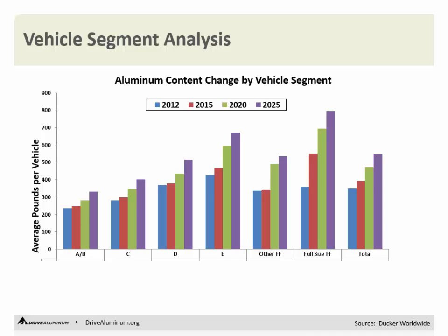And what we see is very significant growth in aluminum content for the full-size, full-frame trucks, also for E-Series vehicles. And it's a fairly continuous, pretty steady growth between 2012 and 2025. There's continued growth in all segments of the vehicle lineup, but the major growth being in, again, the large and full-frame vehicles. But virtually every segment will see significant growth in aluminum content with introduction of perhaps cradles, subframes, and some limited amount of closure panels on the smaller vehicles.